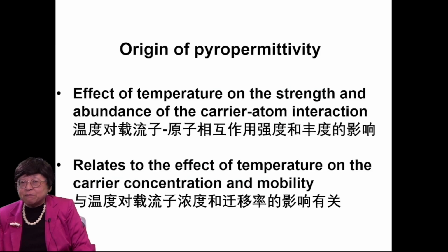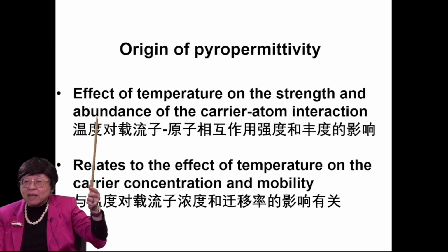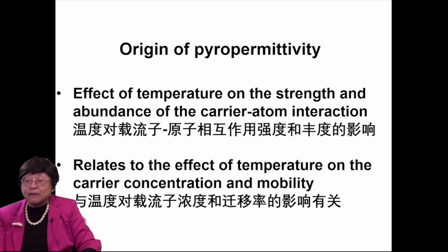The origin of pyropermittivity is the effect of temperature on the strength and abundance of the carrier-atom interaction. Carrier meaning the mobile charges like electrons. Also, the origin relates to the effect of temperature on the carrier concentration and mobility.